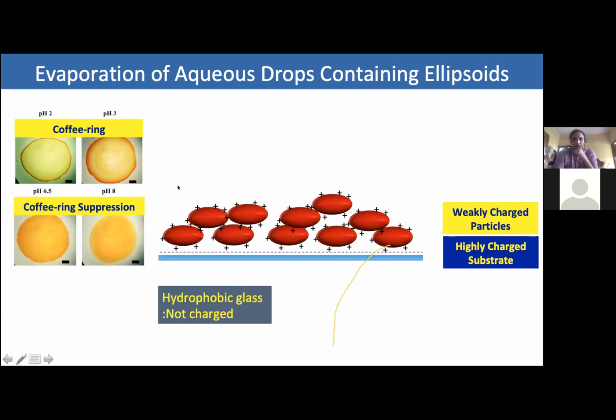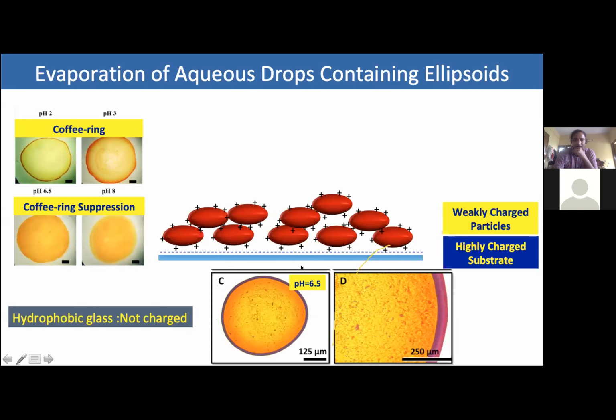Now, what one could do is negate the particle-substrate attraction. That means if I make the substrate hydrophobic, then I can get rid of the substrate-particle interactions. In such a case, we again recover the coffee ring deposit, in spite of the fact that the experiments are done at pH 6.5. So if you compare the pH 6.5 case here and the pH 6.5 case here, in the second case, you have a coffee ring formation. We've been able to enhance the coffee ring effect because the particle-substrate interaction is suppressed in this case.